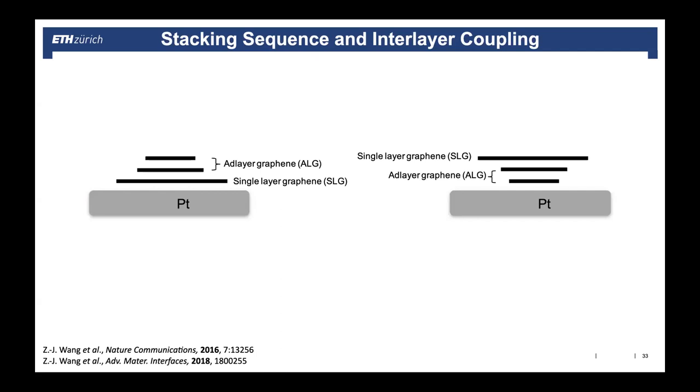of graphene, how is it happening? In some cases, you have a first layer of graphene on the catalyst, and then the next layer grows because the first lifts up and new carbon comes from underneath. For example, in nickel, carbon can segregate from the bulk when you cool down and you form one layer, and then the next comes out. So you get what is called an inverse wedding cake. You can form new layers always below the first layer, close to the catalyst. The other possibility is that you grow graphene and the next layer forms on top, and again on top, and then again on top.